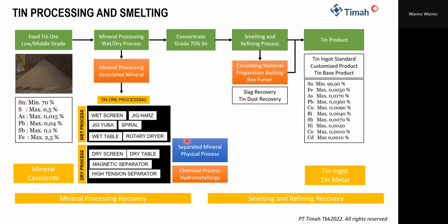So in this slide, we can see that in mineral processing, we will get cassiterite as the tin mineral with a higher concentration, as high a grade of Sn as possible. When the grade is higher, it's very good for the next step, especially in smelting and refining. The grade of concentration will decide the percentage of recovery. If we get a higher concentration of tin, we will get a higher recovery of ingot more easily than with lower tin concentrate.